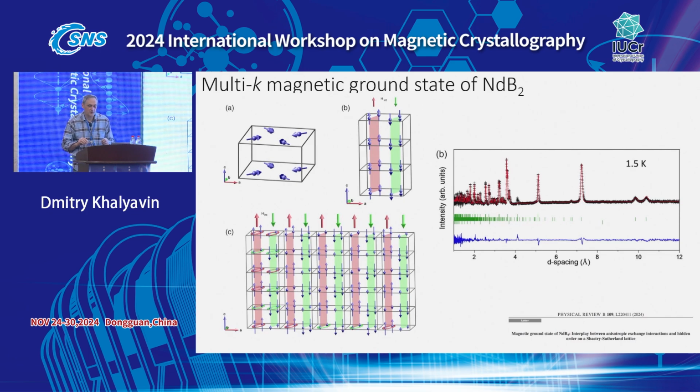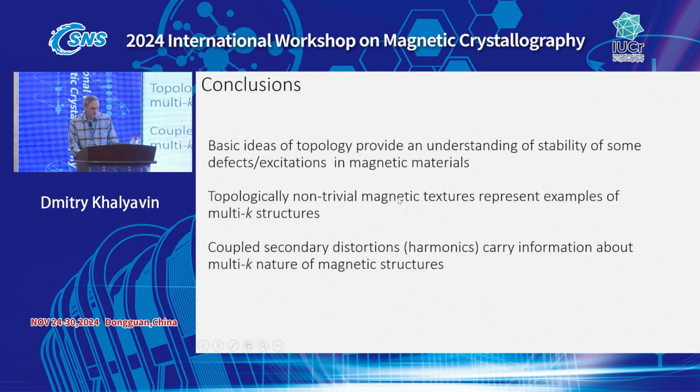So it produces spins along the internal field. It's 3 up, 2 down, and then opposite, 3 down, 2 up, and alternates like that. That's what gives this anharmonic spin density wave, and that's why our second harmonic is huge. It's very big. But again, this logic, what I told you, helped me to sort out this extremely complex case. Okay, I think we can just make some very brief conclusions.